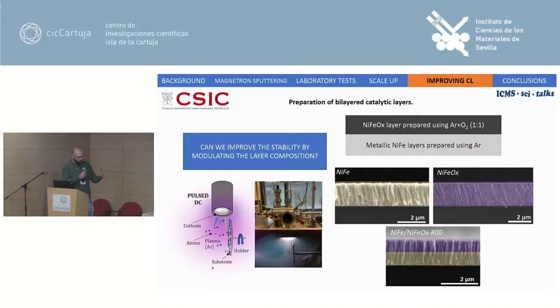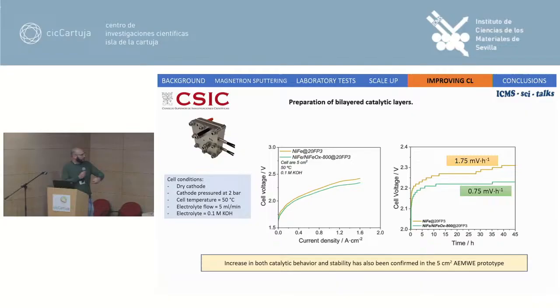And here, to summarize, I have compared its behavior with the original monometallic, monolayer metallic nickel iron catalytic coating. We can see here in the voltage current density representation how the voltage is shifted to lower values. So we are improving the performance of the catalyst. And also the more important property is that the combination of both catalytic layers, the oxide and the metallic, significantly improves the stability, decreasing the degradation rate to under 1 millivolt per hour of voltage increase. This value is more correlated with those values that we can find in the literature for this kind of catalytic coatings.